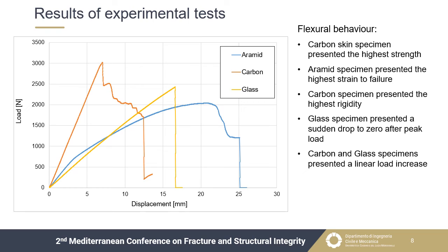The data obtained from the experimental test campaign are reported in this figure, in terms of load versus displacement. In particular, a single curve was plotted for each type of specimen that was representative of the results relevant to the 5 specimens tested for each type. From the experimental data, it can be noted that the highest strength belonged to the carbon skin structure, that reached a maximum load of about 3000 Newton, while the lowest one was obtained by the aramid skin structure,